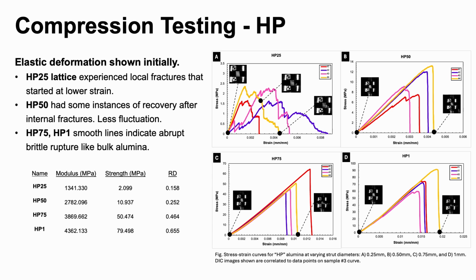A is from HP 25, B is from HP 50, C is from HP 75, and D is from HP 1. So from the stress strain curves, we see that all lattices showed elastic deformation in the beginning of the test. For HP 25, local cracks and fractures initiated at relatively small compressive loads, leading to stress fluctuations throughout the test. For HP 50, there were still some local cracks, but they recovered and there were less fluctuations. For HP 75 and HP 1, we saw that they had smooth stress strain curves that failed abruptly like bulk alumina. And we see that as relative density increased, so did the modulus and strength.